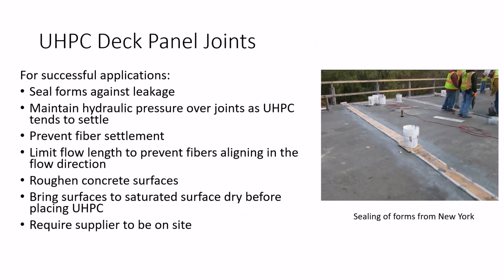The other thing is that if you're pouring UHPC at point A and you expect it to go to point B, and those two points are very far from each other, and UHPC is going to flow a very far distance, then what can happen, and what has been reported as happening, is that the fibers all orient in that same direction of the flow, which is very undesirable, as we really want a random distribution of those fibers. So keeping that flow length short is recommended.